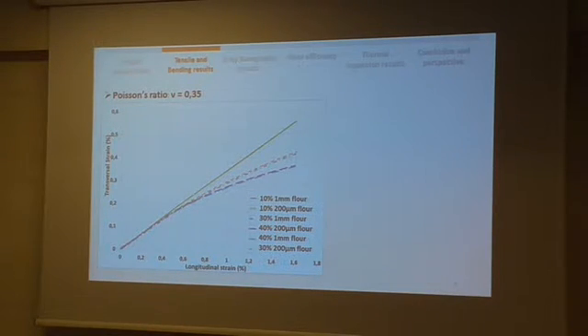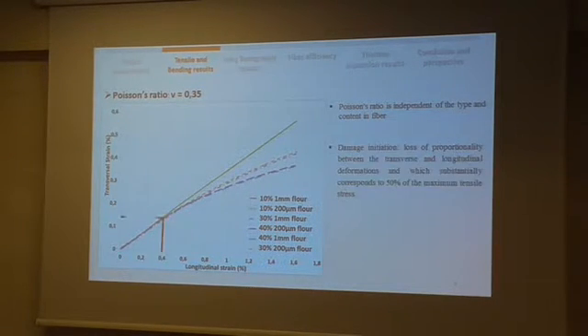Measuring the transversal deformation, we were able to calculate the Poisson's ratio, which is equal to 0.35 for this composite. Seeing the different curves, we can conclude that this Poisson's ratio is independent of the type or content in fiber. We also noticed the initiation of the damage of the composite, which is marked by the loss of proportionality between the transversal and the longitudinal deformation, and which occurs between 30 and 50% of maximum resistance of the composite.